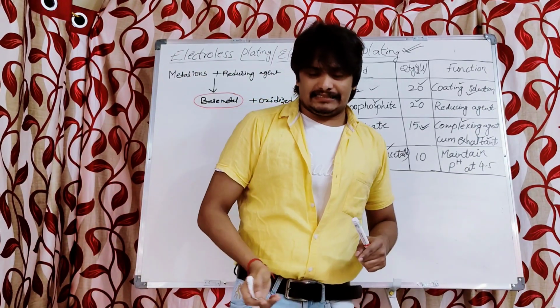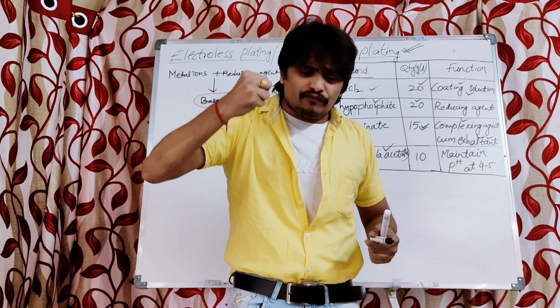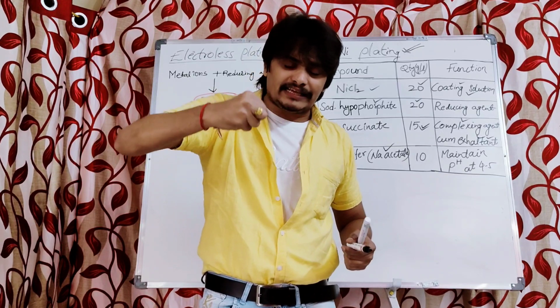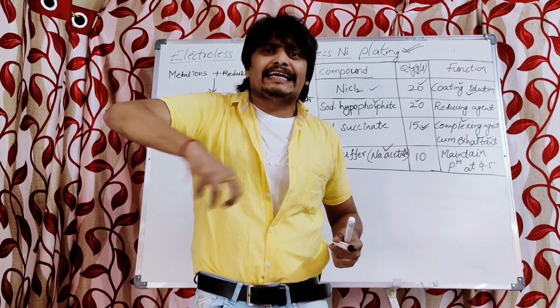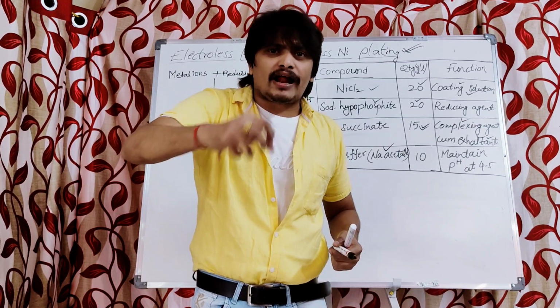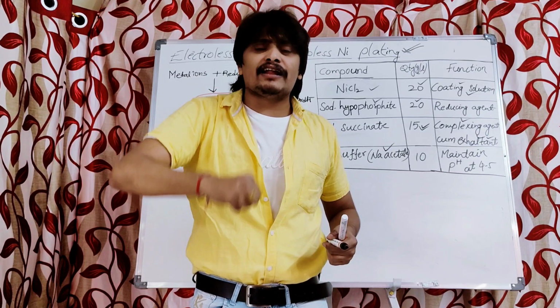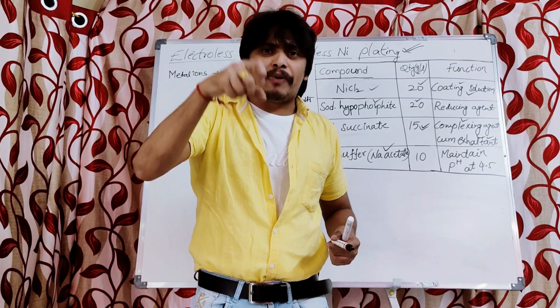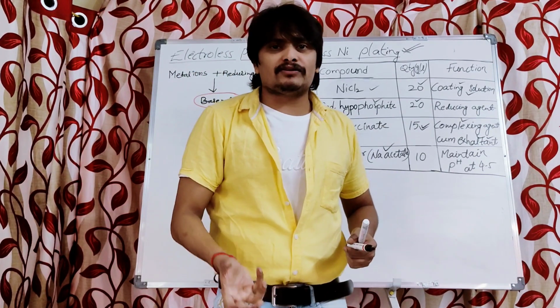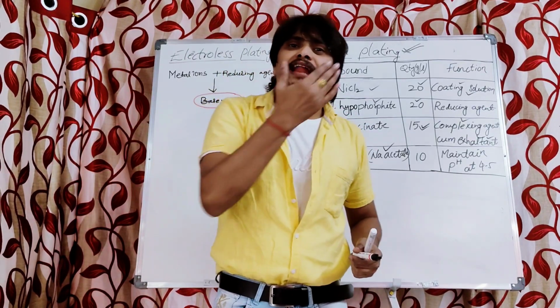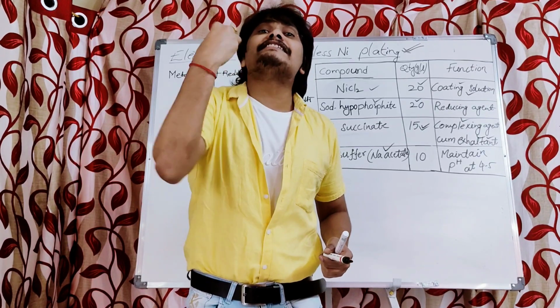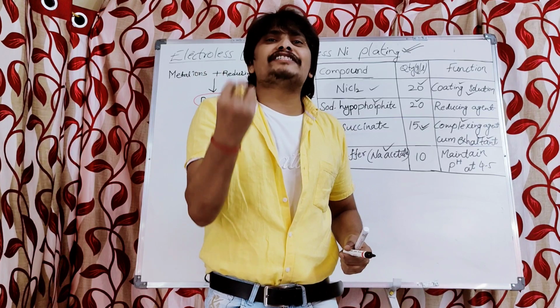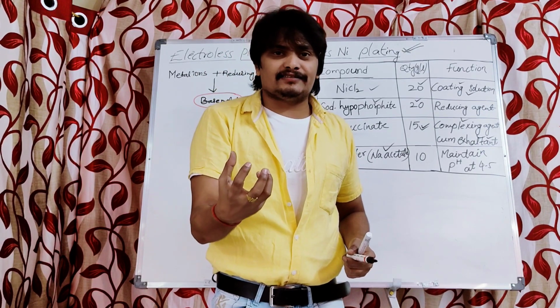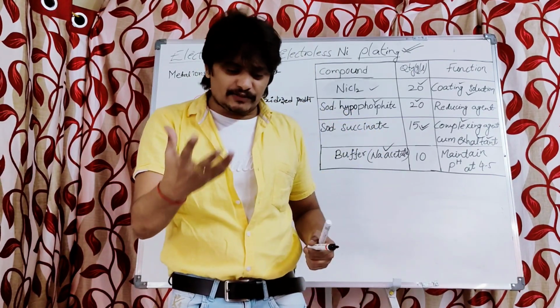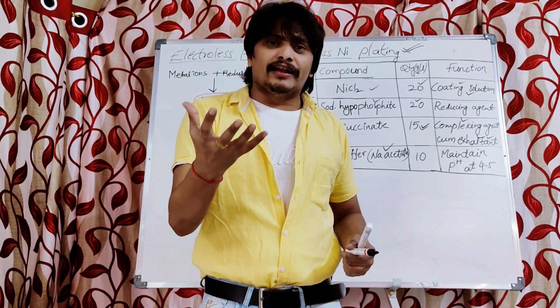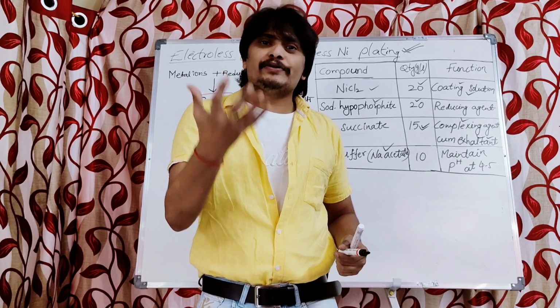So what do you mean by complexing? It is the complexing agent. The purpose of this complexing agent, sodium succinate, in this bath is that it will bind all the other ingredients together. That is, it will bind the nickel chloride salt, sodium hypophosphite, sodium acetate and all the other ingredients along with the sodium succinate. So it is a binding agent. Not only that, it will act as the exaltant. Exaltant means it is a stimulator which will stimulate the reaction between the coating solution and the reducing agent. Stimulates means it encourages the reaction between the coating solution salt and the reducing agent.